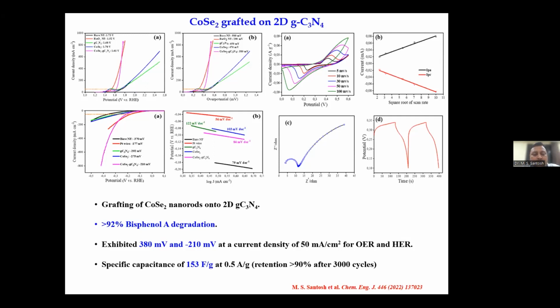While developing these materials, we also subjected this to photocatalytic degradation of bisphenol, where we obtained 92% and higher degradation efficiencies. And we also found 380 millivolt at current densities of 50 milliamps per centimeter square for OER and HER, and a specific capacitance of 153 Farad per gram for the supercapacitor studies. The most important and interesting aspect is that in spite of using this as an electrode material and running it for several cycles, the retention of this material was greater than 90% even after 3000 cycles.